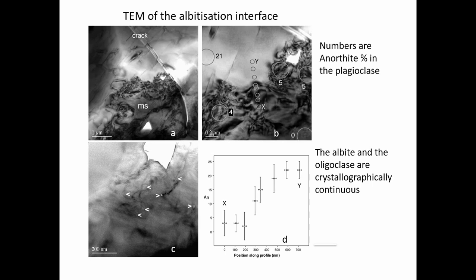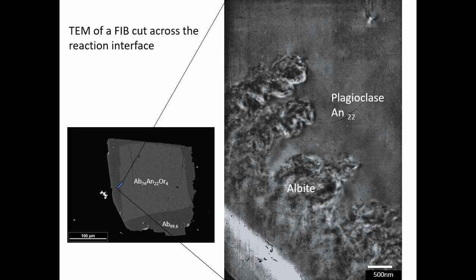The rim looks rather turbulent. That's because it's highly porous. The original phase did have pores, but not pores at the scale that we could see as well as in the albite. So again, during these replacements, we're looking at the porosity formation associated with the formation of the new phase. There's a TEM cut again. That's a zoom in of that interface. Albite, almost pure on the left, the original plagioclase on the right.